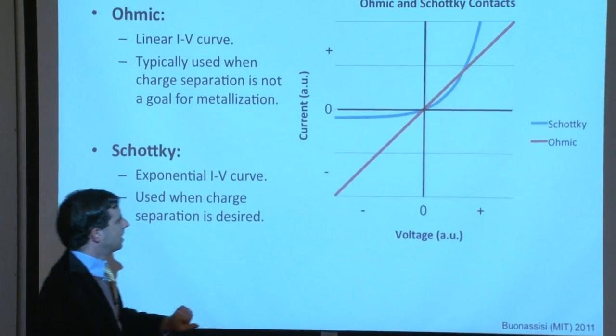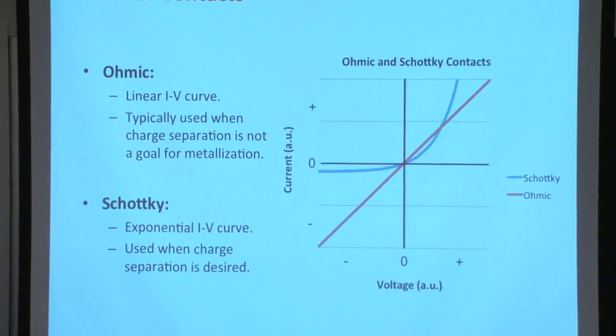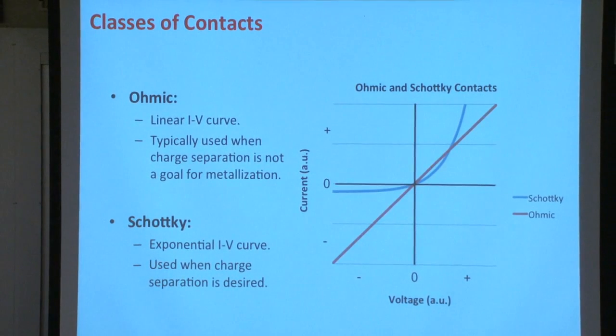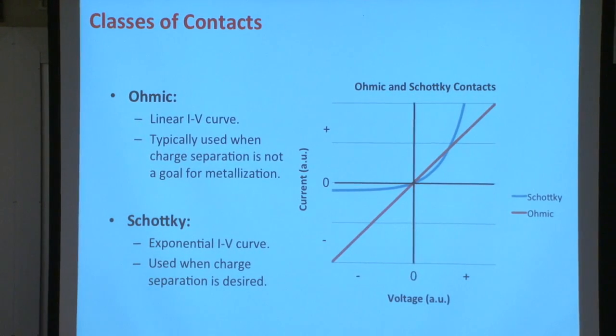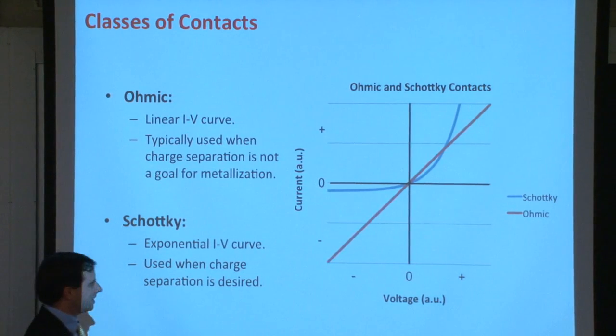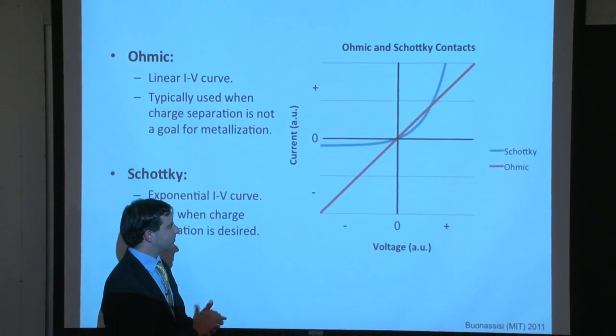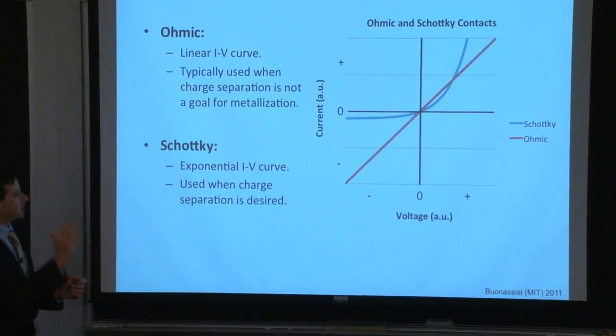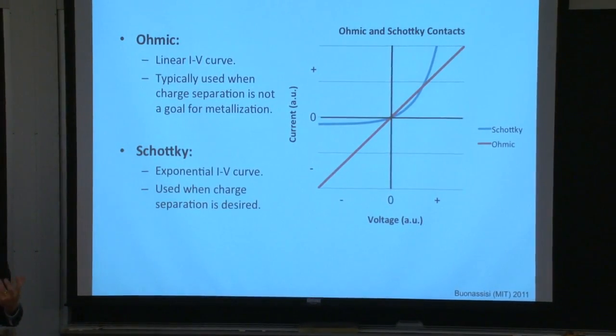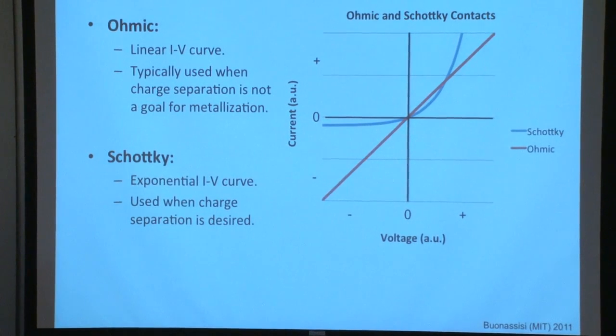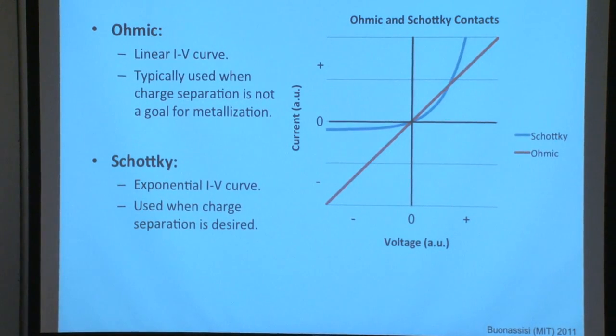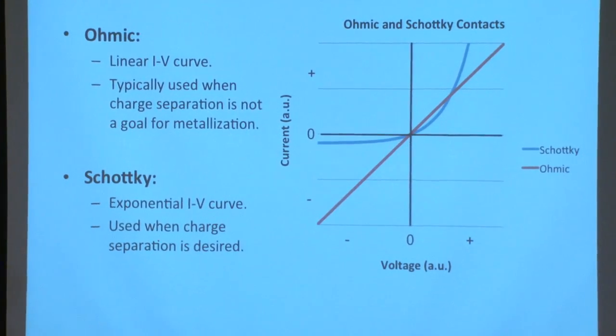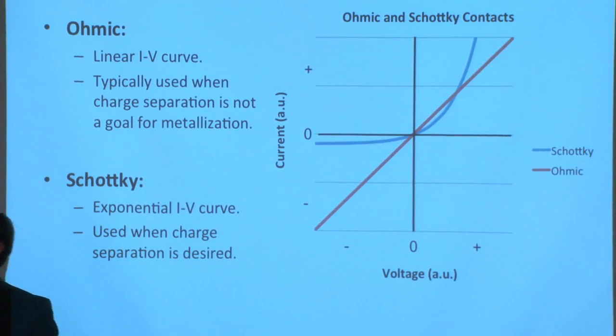So when we see an exponential current voltage response, we should immediately think about some barrier involved in our system. And as we begin biasing this device, in this case a semiconductor metal junction, as we begin biasing the semiconductor versus the metal, we begin seeing an exponential current response. We should imagine that there must be some barrier in between the metal and the semiconductor. And we'll explain how that barrier comes into being. So again, just to recap, making sure we hit all the points, ohmic linear IV curve, and ohmic contacts are typically used when charge separation is not the goal for your metallization.